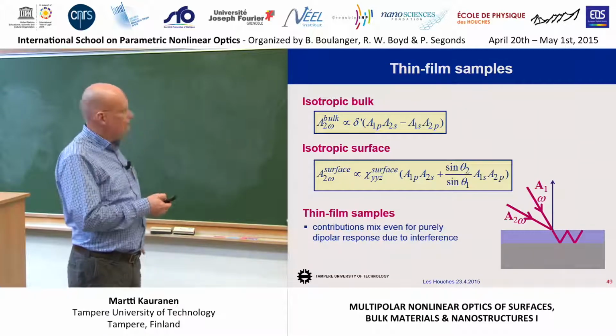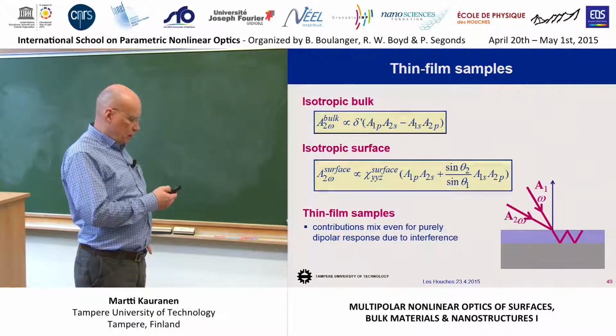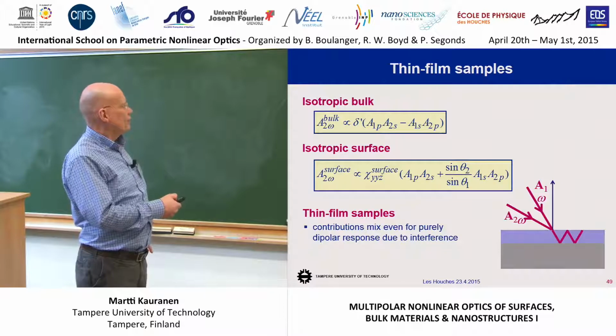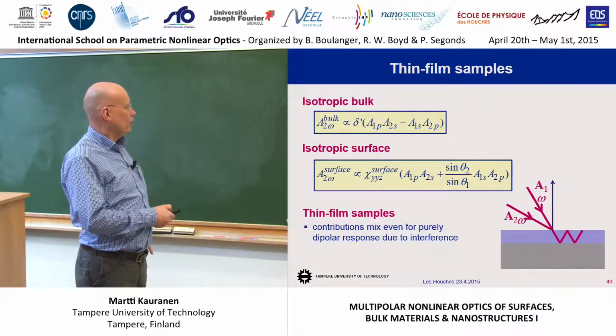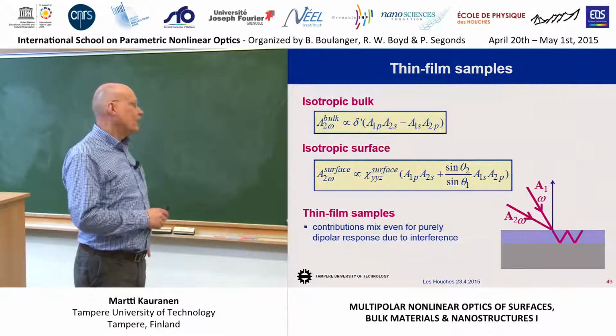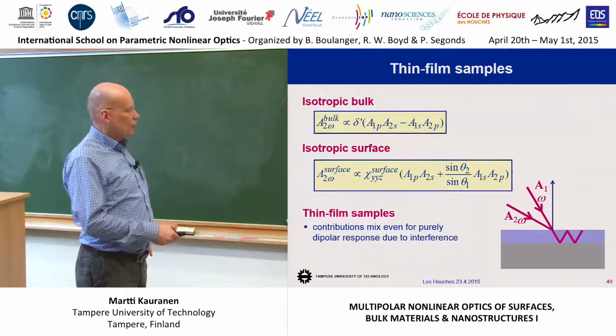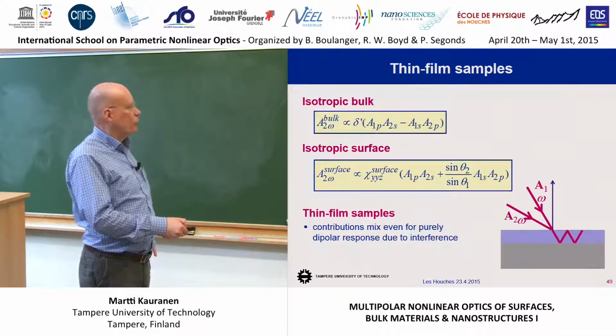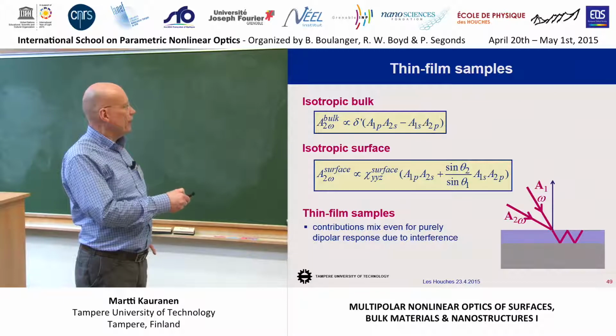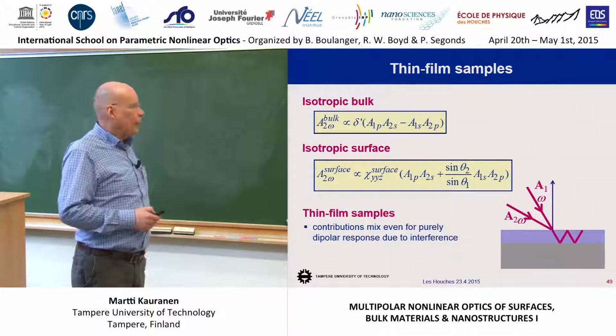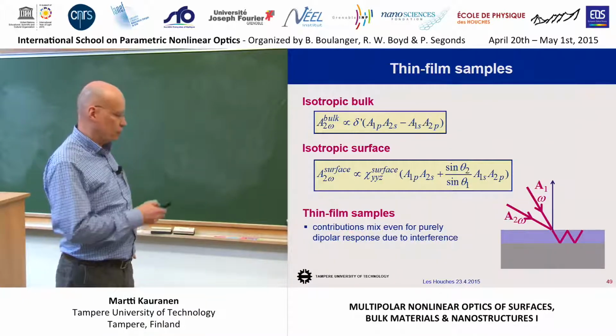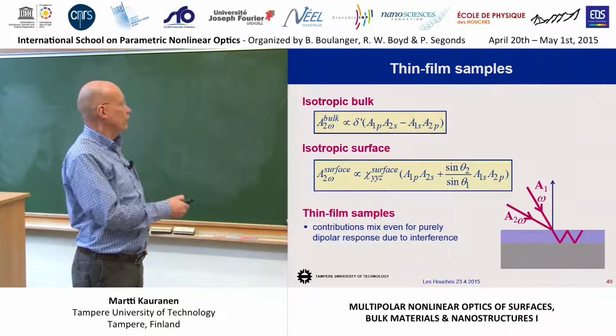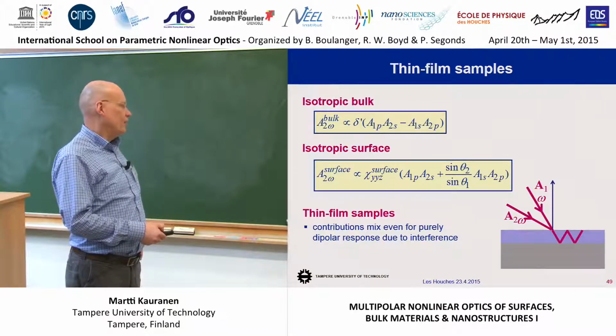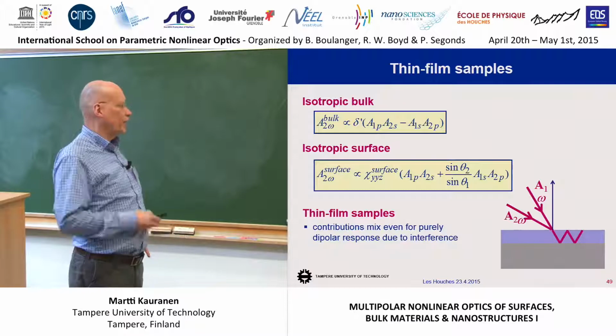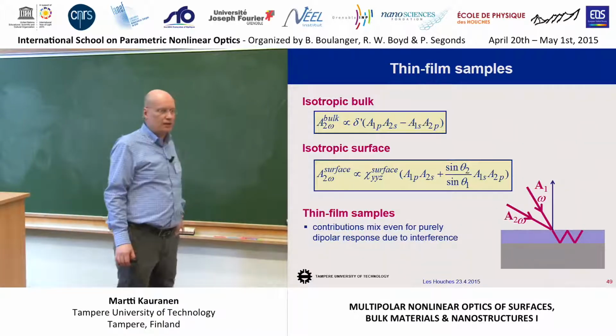If you have a thin film sample, there's a really simple measurement where you measure S-polarized signals and just compare the in-phase and out-of-phase contributions to see the relative weights of the surface response and bulk response. Unfortunately, we have just found out that it fails, because when you get multiple reflections in the thin film, that leads to phase differences between the different field components, and therefore these two contributions, whether in phase or out of phase, are not so well separated anymore. We have even shown, for a case where we expect only a dipole response, that when we do a measurement, we get something that looks like a bulk response, but using a really detailed model that includes all the multiple reflections, we can explain everything using just the dipolar response.